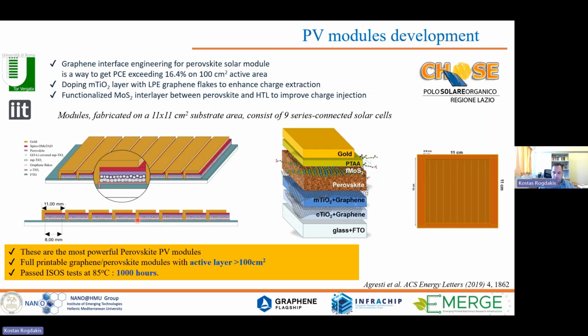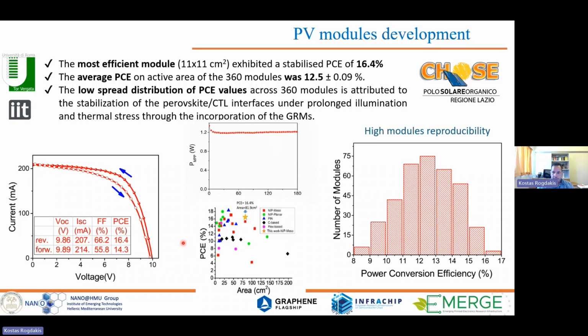At the beginning, for each cell and module, we implemented the ISOS tests at 85 degrees and we passed the required tests. Then we integrated many cells, 11 cells per module, and we fabricated 360 modules. This is the average PCE, power conversion efficiency, per module. The average value was around that time 12.5%, with a distribution of the values around this 12% mean value. Of course, this is not like a conventional technology like silicon. So we have a distribution that is expected for a low technology readiness level technology. Also, the hysteresis was not so bad.